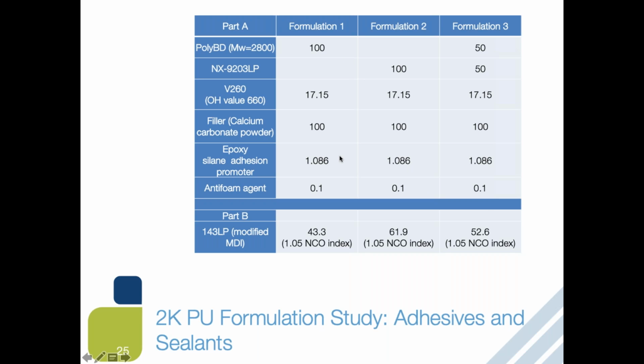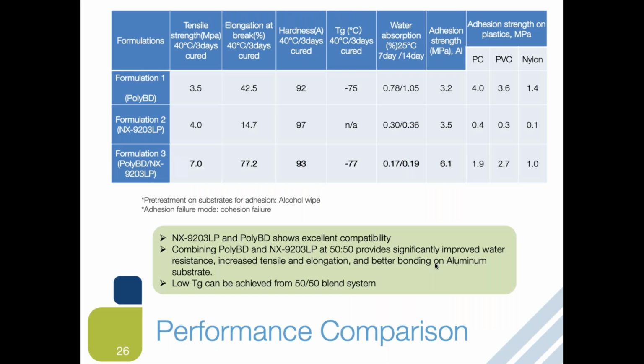So in here, there are three formulations. Formulation 1 uses 100% poly-BD, and formulation 2 uses 100% NX9203 LP. In formulation 3, we mix poly-BD with the 9203 at 50-50. These are cured with modified MDI at an isocyanate index of 1.05. From these formulations, we collected tensile performance data, hardness, Tg, water resistance, and adhesion.